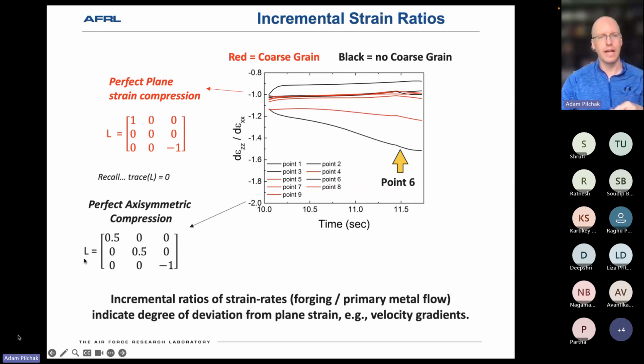Sorry, I forgot to tell you, L is the velocity gradient that we're going to use to drive the crystal plasticity. But in axisymmetric compression, any of the strain I put in the compression direction is balanced by equal strains in all directions in the radial plane. So that's what's represented by these 0.5s here. So you get a cylinder going to an axisymmetric pancake, essentially.